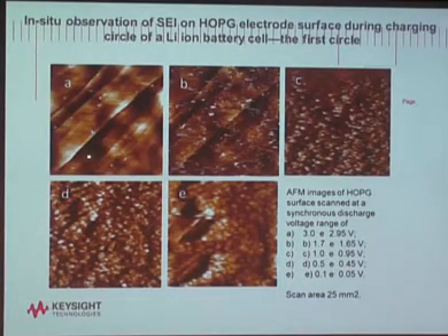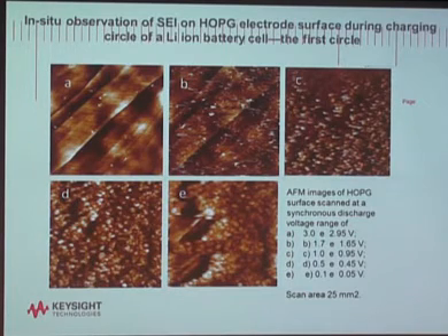This is the very first experiment we did. And you see a lot of noise here, because at that time I did not figure out the vibration isolation yet. So you have about a 1.5 angstrom noise. So here's what happened. We're charging the electrode, which is graphite, at 3 to 2.95 volts. That's the graphite surface. You have a little bit start to happen. At 1.7 to 1.65 volts, as you charge it, you start to form a little cluster here, and the graphite still has no change. We believe something happened, and we believe it is the decomposition of lithium alkyl carbonate from a polymer on the surface, at 1.0 to 0.95 volts and so on and so forth.